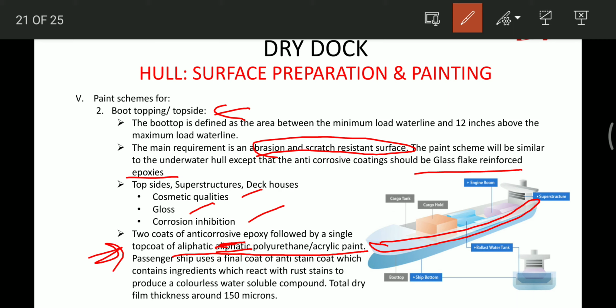Then passenger ships use a final anti-stain coat which contains ingredients which react with rust stain to produce a colorless water soluble compound. Then the total dry film thickness is around 150 microns. So friends, basically 2 coats of anti-corrosive epoxy paint are applied, followed by a single coat of aliphatic polyurethane or acrylic paint. The main difference is that the anti-corrosive paint over here should be glass flake reinforced epoxies.